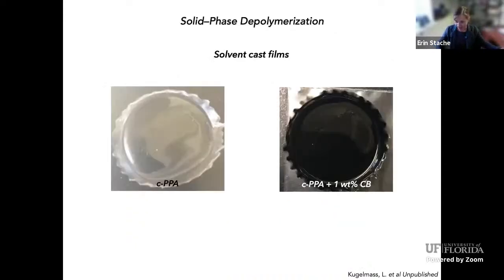So we started with solution phase because that's easiest: just dissolve the polymer, add some carbon black and call it good. But in practicality, we don't really want to dissolve all the polymer and then irradiate it with light in solution, especially not in DCE, which is a chlorinated solvent. And so now we're looking into solid phase depolymerization. Liat learned how to cast some different films with and without carbon black. In this film right here, you can see this is just the polymer on its own. It's very clear and transparent, although a little brittle.